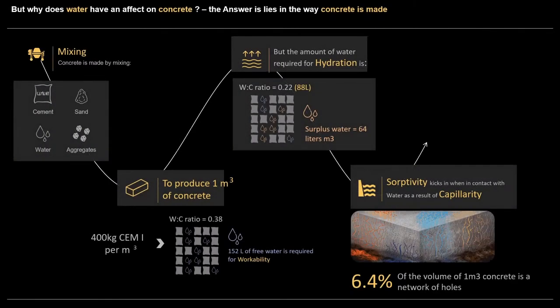Why is this? If we look at a very basic mix now, it's actually quite a good quality concrete. If we look at a mix with 400 kilograms of cement and a realistic water cement ratio of 0.38, so it's a very good quality concrete, that's going to tell us, we do the calculation, that you add 152 litres of water. Actually required to hydrate that cement is considerably less. You need a water cement ratio of about 0.22 or 88 litres. So in this very good quality concrete, we've got a surplus amount of water, 64 litres in a cubic metre.